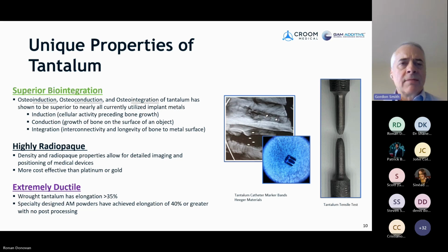Looking at some of the mechanical properties of tantalum, tantalum offers a very high ductility, which lowers the risk of brittle fracture, with wrought tantalum demonstrating in excess of 35% elongation at break. Now, we have found it very interesting that when printing with our tantalum powders, off the printer, we are seeing 40% elongation in the build direction. So a little bit better than what you would expect from wrought tantalum.